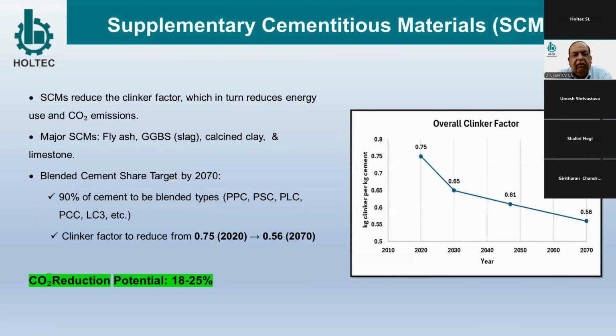Now, the next important lever is supplementary cementitious material. So basically our aim is to reduce the clinker consumption, clinker proportion. Currently in 2020, the industry average is 0.75, and this is targeted for 2070 as 0.56. That will essentially use slag, fly ash, calcined clay, limestone, increase in proportion of that, and increase in proportion of blended cement to 90%, and reduction of clinker factor from 0.75 to 0.56. So this has a CO2 reduction potential of over 18 to 25%.